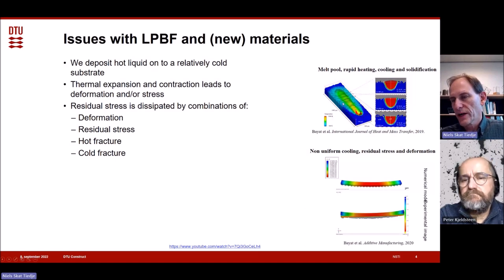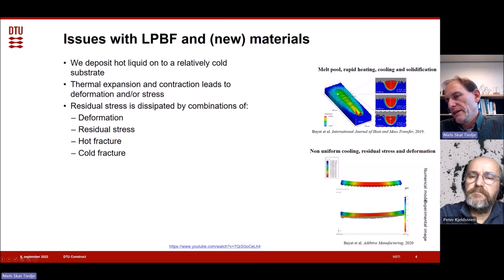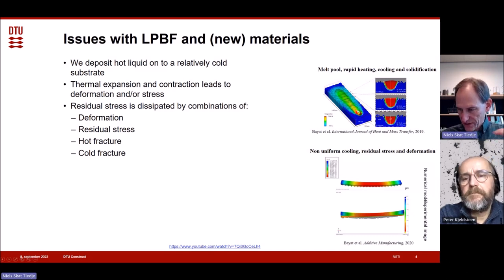On the right here, we see laser powder bed fusion printing, metal 3D printing of materials. We have a laser that runs across a powder and melts. It's basically a welding. And you have cold material out here, hot material out here. When the melt solidifies, it contracts and draws the casting, or the weld or the 3D part together.